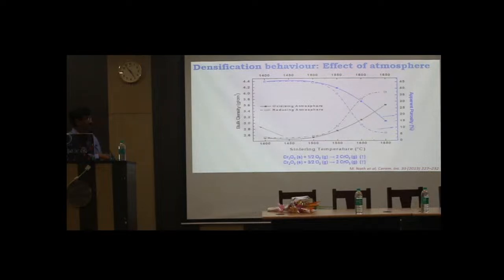You see, at the same temperature when you use the reducing condition, the dotted one is the reducing condition, the porosity level is reduced from 15%, with all other parameters the same. The same sample shows 5% porosity. Still it contains 5% porosity. This porosity means the apparent porosity. So to improve the density further, we use some additive and then sinter it.